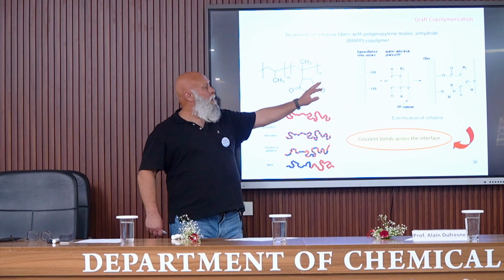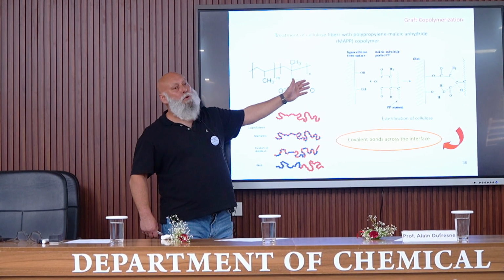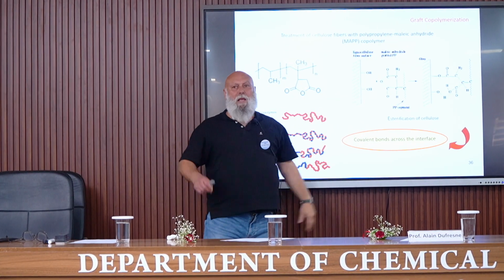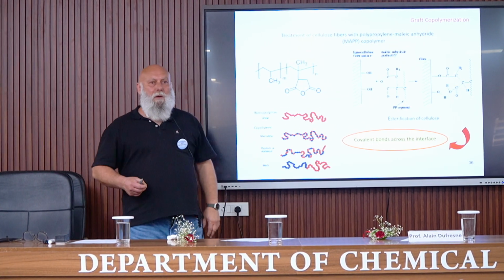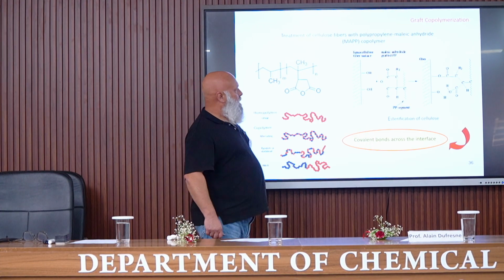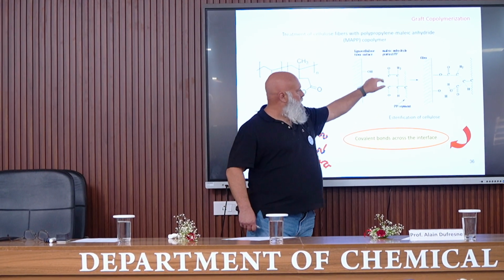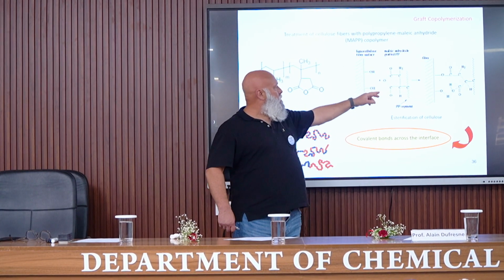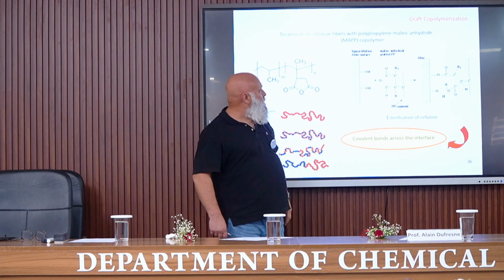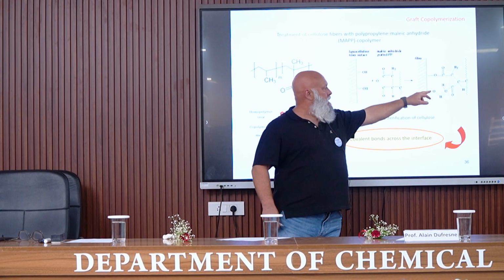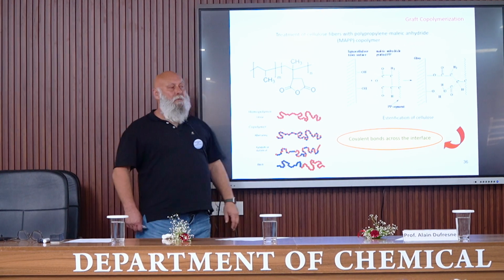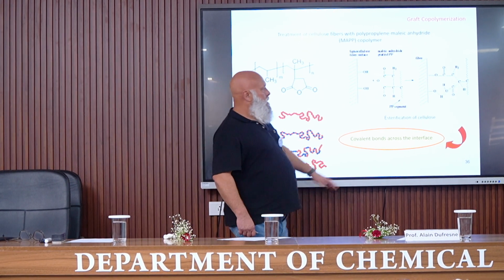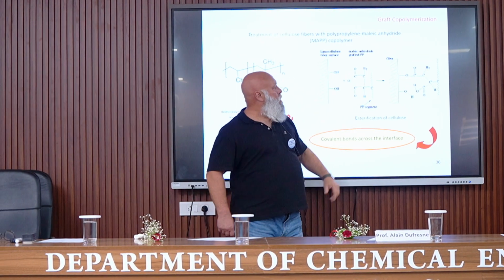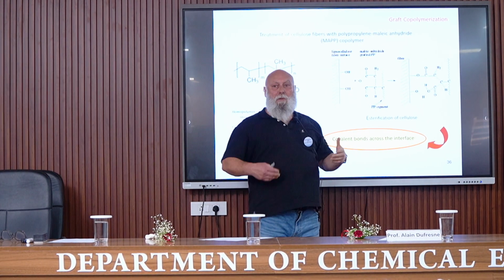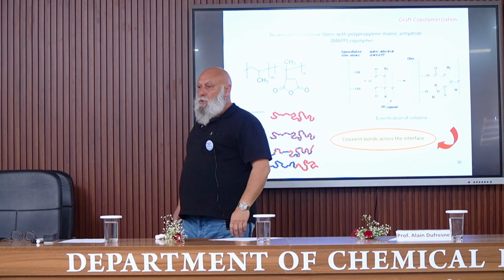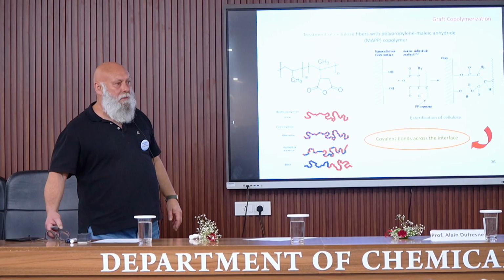It is generally a copolymer, or it can be a random polymer also, that contains only a few percent of maleic anhydride units. And you have here the shell, so this group, maleic anhydride group, is attracted by the OH group on the surface of natural fibers. It can be chemically grafted or physically adsorbed, and then the rest of the macromolecule or the copolymer consists, for example, of polypropylene, and of course, there is a good compatibility with the polypropylene matrix.